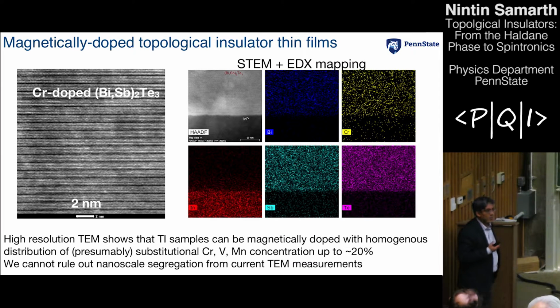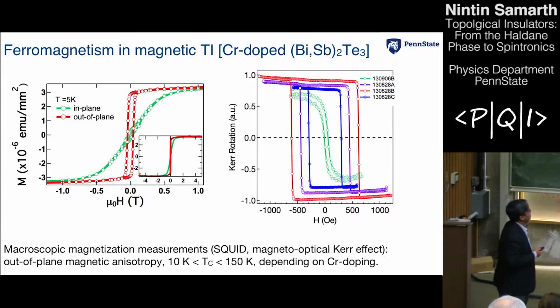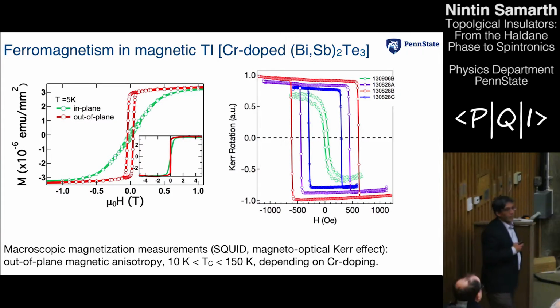To the extent possible with our current electron microscopy, we don't see obvious signs of any kind of clustering of the chromium into metallic clusters and so on. This is a problem that has plagued some of this field in the past, but it doesn't seem to occur here at any kind of length scales that matter. So they look reasonable, these samples. They're not the best, but they're reasonable. Now, do we break time reversal symmetry? Well, if you're breaking time reversal symmetry, you should see evidence of ferromagnetism. What does that mean?